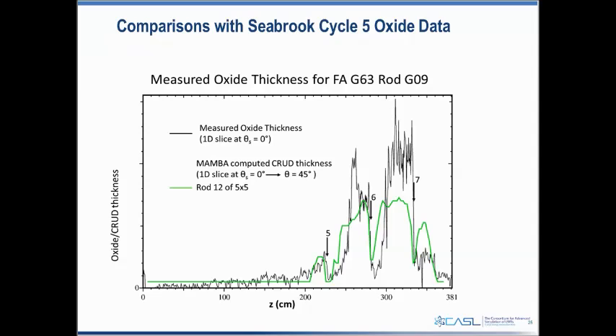We also had some comparisons when we did have the fuel failures. Of course, then we go in and do examinations on the fuel itself. So we measured the combined thickness of the corrosion layer on the cladding surface and the crud deposition on top of that corrosion layer.